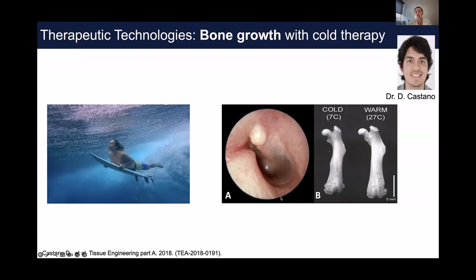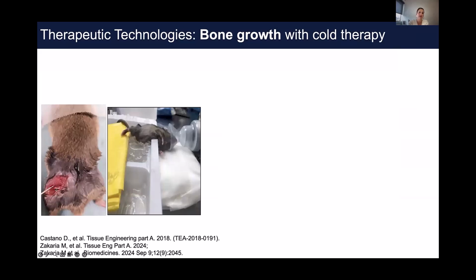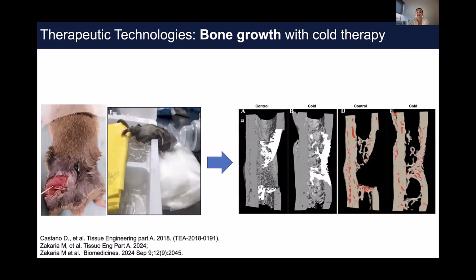But when we looked at all the reports, we saw that environmental cold actually had a horrible negative effect on bone growth. So we were very suspicious about it. So we first created this bone defect model, the same as the other time. We created that cortical defect in the diaphysis of the leg of a mouse. We closed it up, and then every day for 24 days, as you can see here, we took the mouse and soaked its legs for a certain time in cold water. And what we saw, and we were actually amazed, is that not only was the bone completely filled much faster after 24 days than the control, which was not immersed in cold water, but we also had much more blood vessel formation.